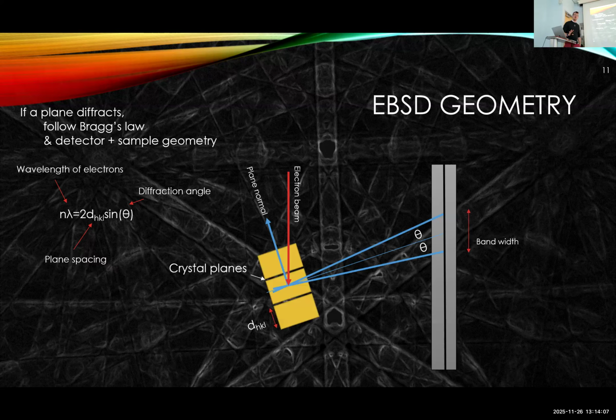In EBSD, it's a subtly different problem in that we shine the electron beam into our crystal, and effectively, if we have the crystal plane running, these black lines are the crystal plane, we can have this center line, which is the direct projection of that crystal plane. And Bragg's law, if the reflector is allowed, says we'll see a band of raised intensity between this angle 2 theta.